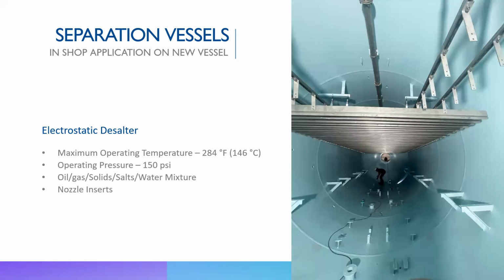So basically we have ammonium chloride corrosion, which is going to affect your stainless steels. And in this service, typically you're going with an upgraded metallurgy, but you're still having that problem. So what industries do is they wash out their salts before it enters the process. But you need to protect that vessel that's washing out the salts, because that's obviously a very corrosive service as well. So you know that it's going to affect your stainless steel. So can you look at the other options of carbon steel coated with a coating that can handle the salt service? So that's what we do here. So two ways we can help with ammonium chloride corrosion is to coat it at the source, before it goes into the ammonium chloride aspect.